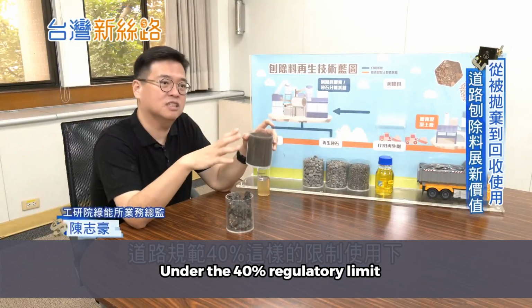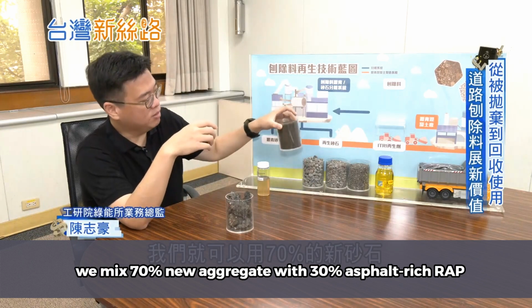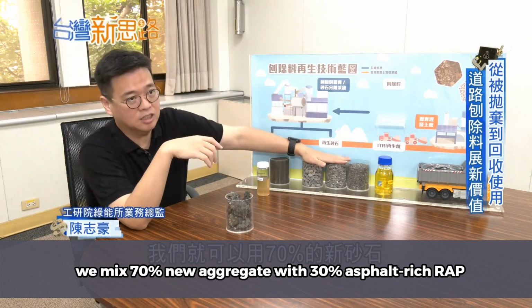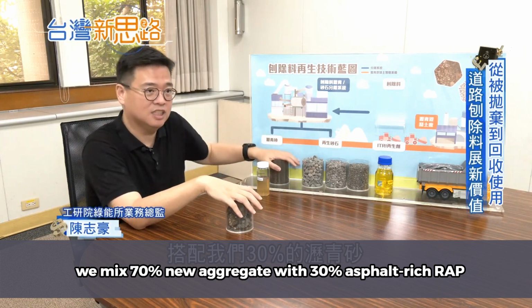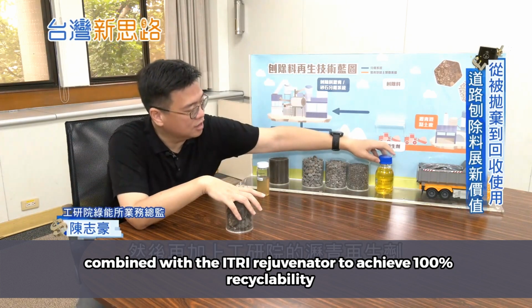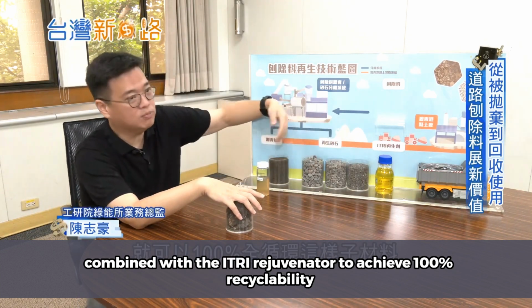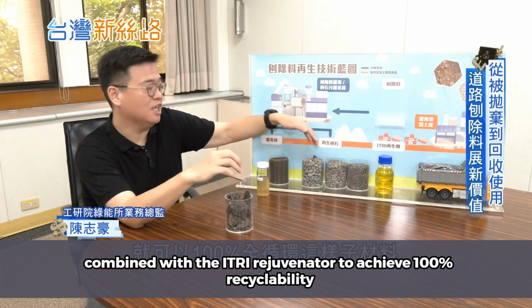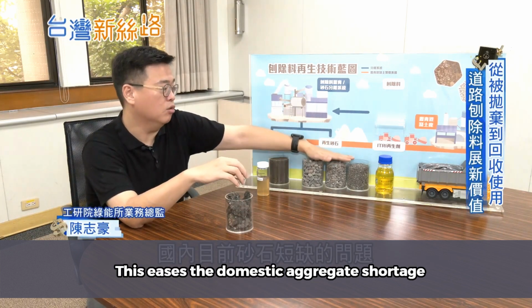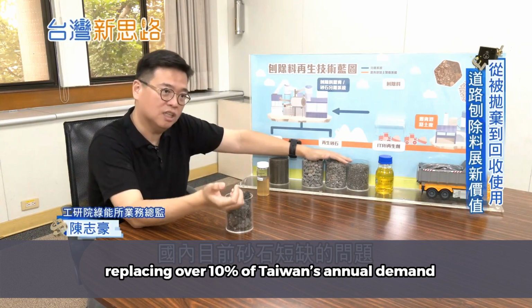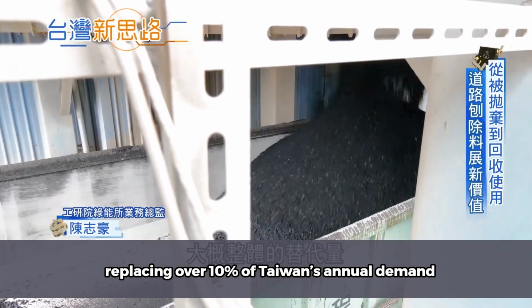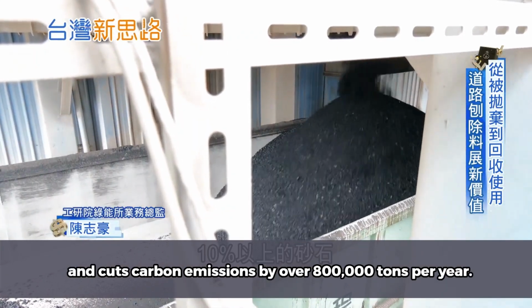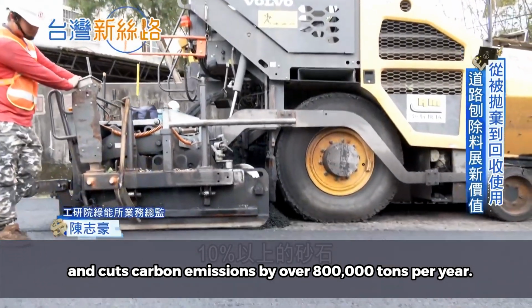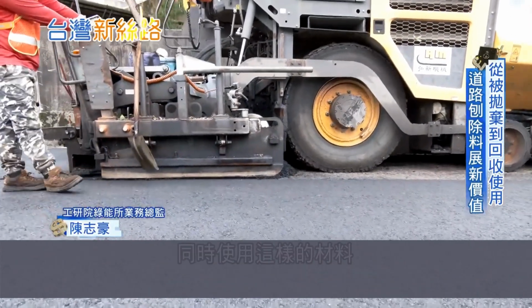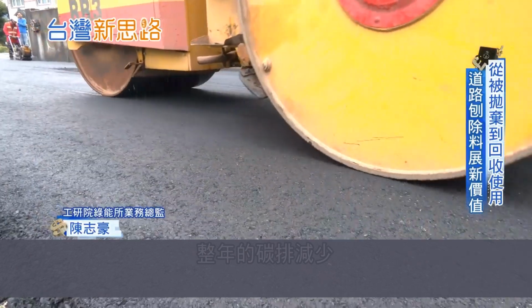Under the 40% regulatory limit, we mix 70% new aggregate with 30% asphalt-rich RAP, combined with the ITRI rejuvenator to achieve 100% recyclability. This eases the domestic aggregate shortage, replacing over 10% of Taiwan's annual demand, and cuts carbon emissions by over 800,000 tons per year.